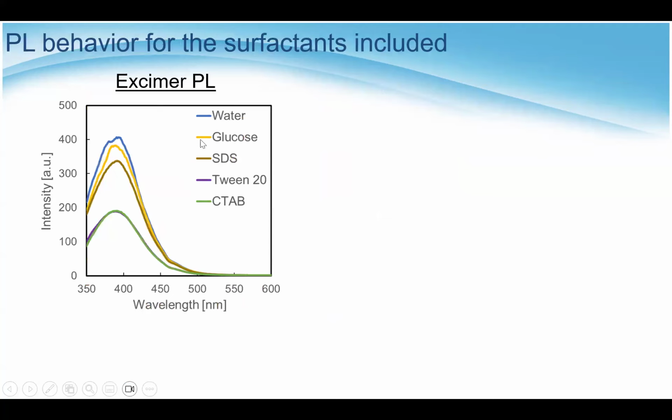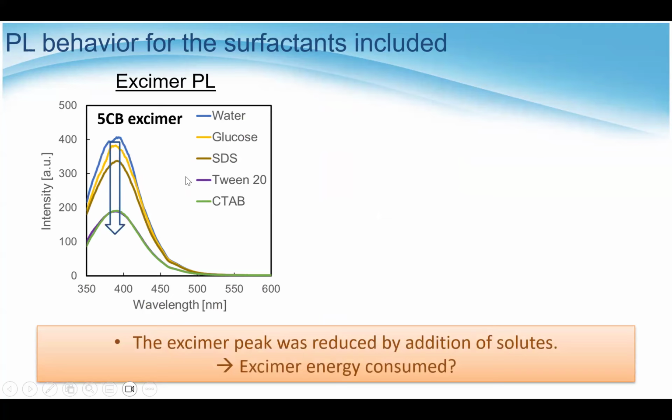During this process, we checked the excimer peak in the PL. In the water case, it is this one. And when some surfactant molecules or solute molecules are there, the 5CB excimer peak was actually reduced. So it seems like the excimer energy is consumed.